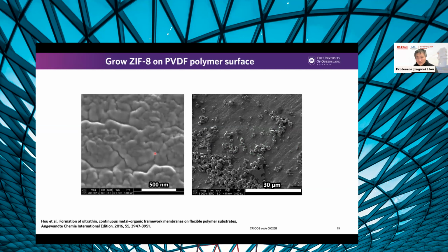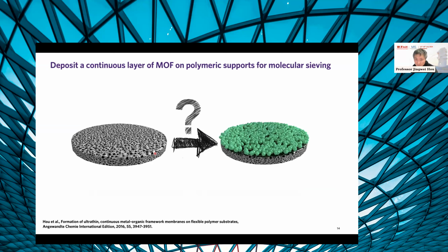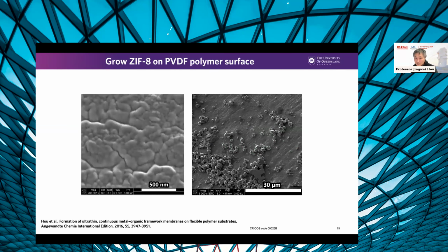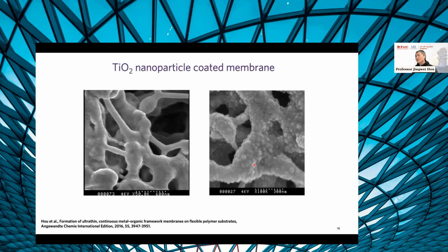That's pretty hard. So if we want to grow a MOF on top of a polymeric substrate, this is what we usually end up with. Typically, we want to start with something commercially available. Say we start with a PVDF membrane, which has been widely used for water treatment. But anything that has been widely used in industry typically is not really reactive. They're quite inert, quite robust. That means they don't really like MOF to be grown. So this is what we can get after we soak the PVDF membrane into the MOF precursor solution. We try to grow MOF on top, but we don't get anywhere near a coherent continuous layer. We will never use this membrane for gas separation because it will never achieve any separation efficiency. So how can we solve that?